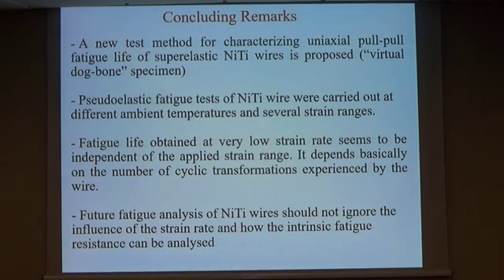We carried out some pseudoelastic fatigue tests, and the results mainly show that at very low strain rates, under isothermal conditions, fatigue life depends basically on the number of transformation cycles. It seems not to depend on the strain range or mean strain. Of course, we have to continue later, because this kind of experiment is long.